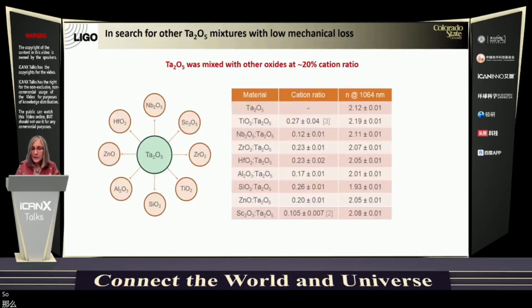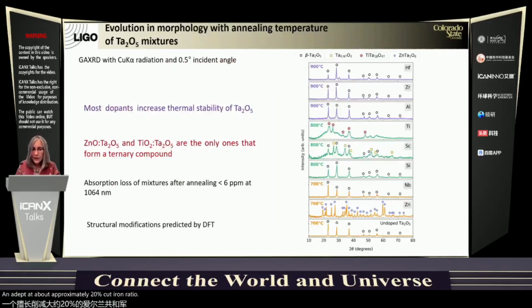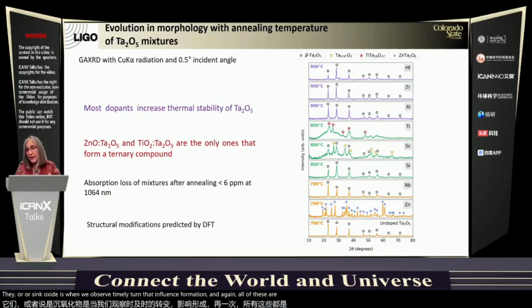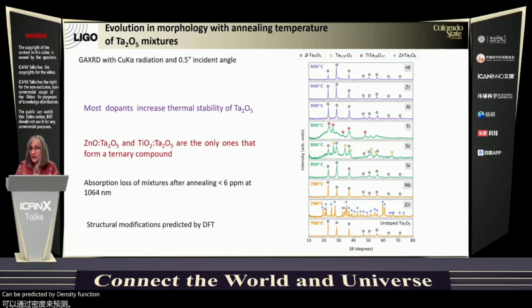So motivated by these results, we investigated the doping of tantala with other oxides at approximately 20% cation ratio. And what we learned is that most dopants will increase the thermal stability of tantala, but only in the case in which we dope tantala with titania or zinc oxide do we observe ternary phase formation. And again, the evolution of the films with the different dopants can be predicted by density functional theory models from the Materials Project database.